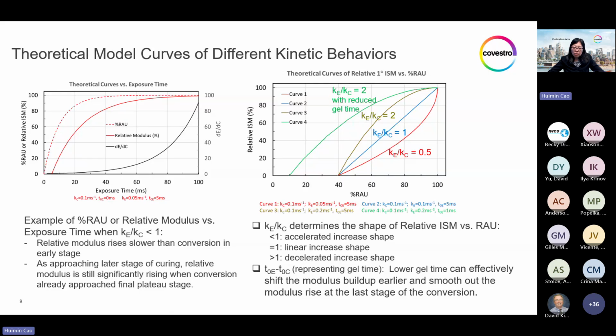It should be noted that this conventional curve in red, which means a sharply rising in situ modulus versus RAU, does not really mean the modulus is sharply rising at the last stage of the reaction time. From the left chart, plotting modulus and conversion versus exposure time, you can see both are slowing down following first order kinetics. It's just that the conversion reaches a plateau first, while the modulus is still rising. This is the reason for the sharp rising trend when plotting modulus versus conversion.